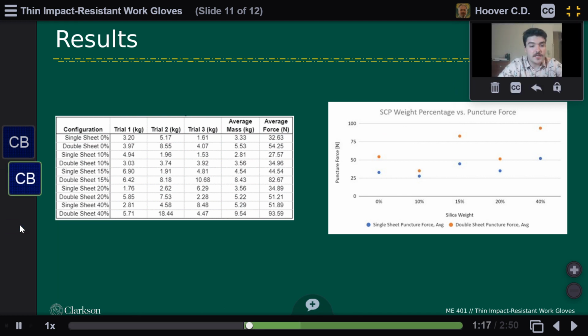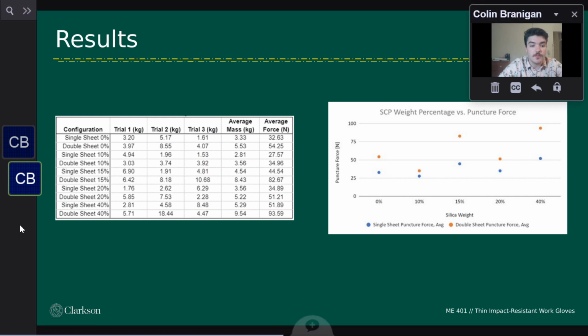We tested 10 different material configurations 3 times each, totaling to 30 separate trials. Each trial lasted up to 20 seconds and recorded between hundreds to thousands of mass readings in intervals of milliseconds. The table on the left shows the maximum load acting on the Kevlar in each of these trials. Immediately after the material was punctured, a load was no longer applied. The figure on the right shows the average maximum puncture force of each material configuration in newtons.